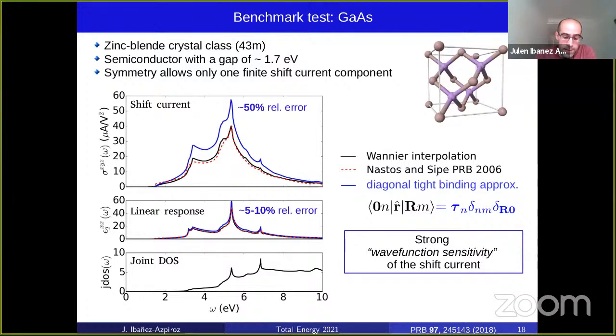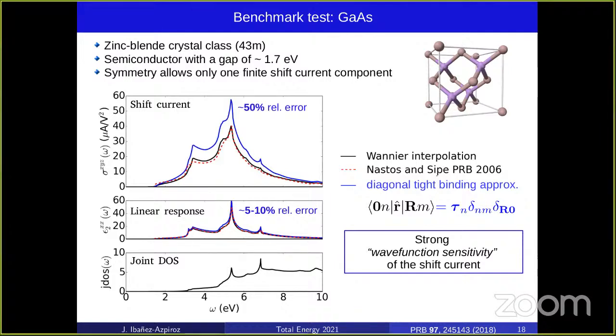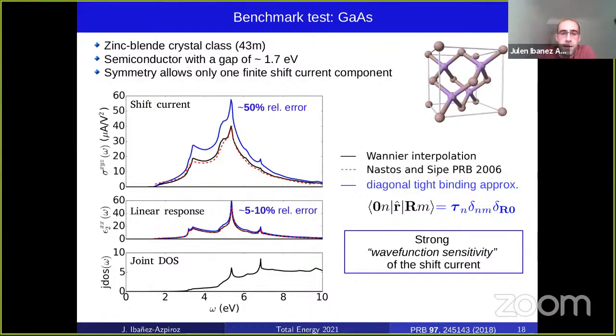So this approximation is good for the linear response, but not for the shift current. It does have a big impact on the shift current spectrum because it induces a relative error of approximately 50%. So for the numerics, these off-diagonal position matrix elements are important for the shift current, and even more, they are a quantitative proof of the strong wave function sensitivity of this particular response.